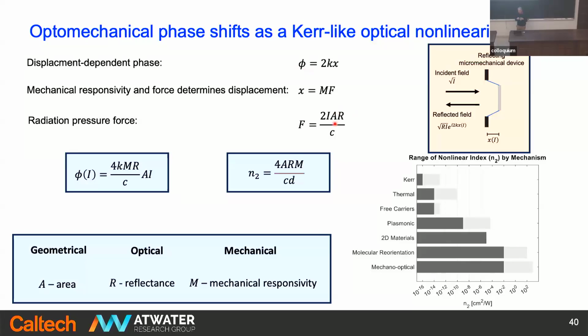Mostly with materials, the nonlinear optical coefficient, like the Kerr coefficient or the Pockels coefficient, or due to multi-carrier absorption, these are properties of the material. But here this is proportional to an extensive property, which is the area. So for our little oscillators that are about 20 or 30 microns on a side, the attributable nonlinear index is among the highest of any material you can make by chemistry or physical methods. It's orders of magnitude larger than the Kerr, N2 nonlinear index coming from the Kerr effect.